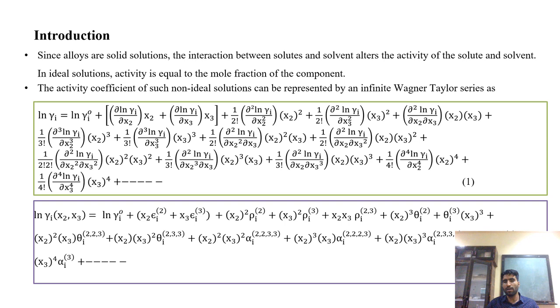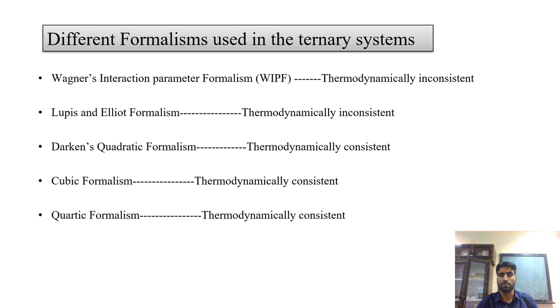As far as these metallic systems are concerned, we usually deal with alloys. Alloys are basically solid solutions. In case of an ideal solution, the activity is always equal to the mole fraction. But in case of a non-ideal solution, there is a deviation from ideality, and in such solutions the activity coefficient can be represented by an infinite Taylor series — that is Wagner's Taylor series, shown here in equation 1. The nth differentials can be represented by the symbolic representation shown below.